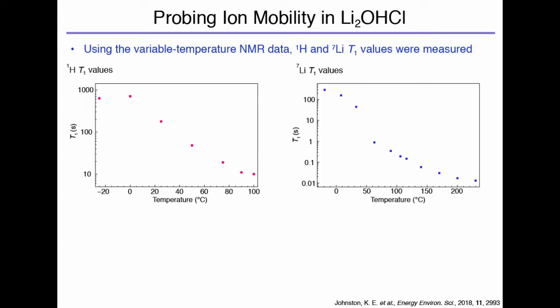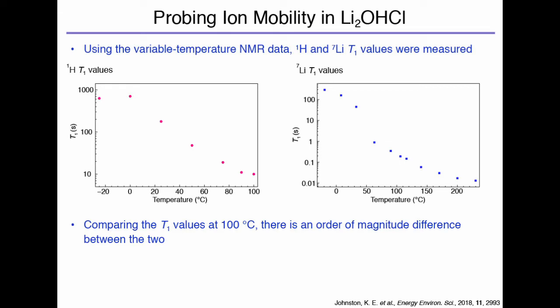So we can then look at something known as our T1, which is looking at relaxation. So it's looking at that lithium and seeing what it's doing, how it's relaxing and how it's changing over a period of time, and how the temperature's affecting it. And what we can do is plot the T1 values for both proton and for lithium. And all we want to do is compare these at the same temperature and see what they tell us. And if you look at the two values at 100 degrees C, there's an order of magnitude difference in the numbers.